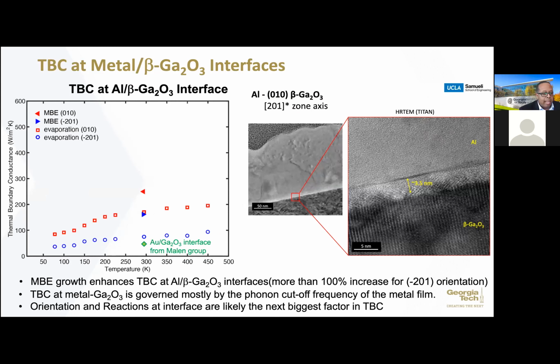And so I want to go ahead and start wrapping up. The last one that I'm going to mention here is as we begin putting metals down, again, we can deposit metals by things like E-beam evaporation. We could also deposit metals by MBE. The interesting thing that we've been finding in our work is that when you deposit metals by MBE, you actually get this dramatic increase in the thermal boundary conductance.